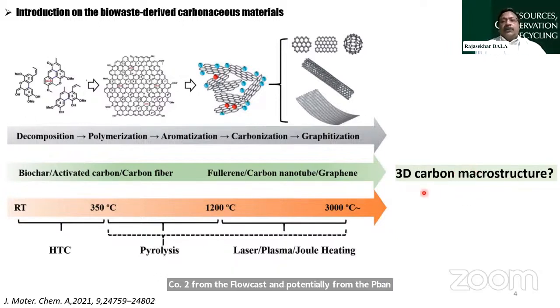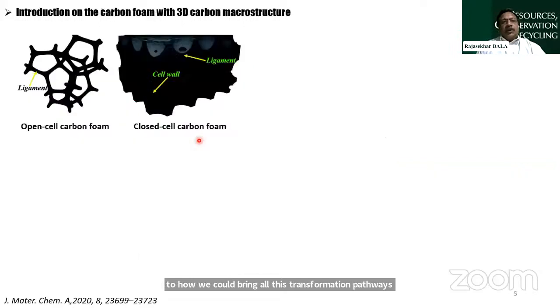So in order for us to get the 3D carbon macrostructure, we have to address all these transformation pathways in one go, which would cut across, for example, decomposition of bio-macromolecules, breaking them down into smaller fragments. The smaller fragments in turn will undergo polymerization, eventually leading to aromatization, meaning integration of different aromatic compounds that we have in the breakdown products of bio-macromolecules. And that in turn will lead to high density carbon, in other words, carbonization, and eventually leading to graphitization, which is an important precursor or a requirement to form 3D carbon macrostructure. So I will tell you more about how we could bring all these transformation pathways together using a novel technology, which is what we have published in our paper.